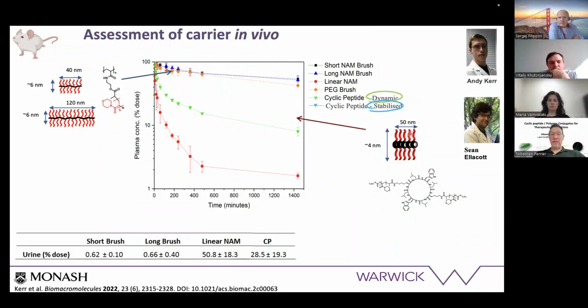But eventually, the conjugates are going to fall apart, so they're going to shave off the end group bit by bit, and slowly they're going to be excreted. And you can see in the specific time, what we're looking at is about 30% of our nanotube is excreted within 24 hours. Now, this is the dynamic system. So that's a system where the graft is 100% hydrophilic.